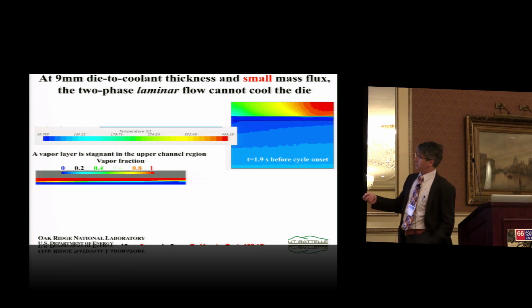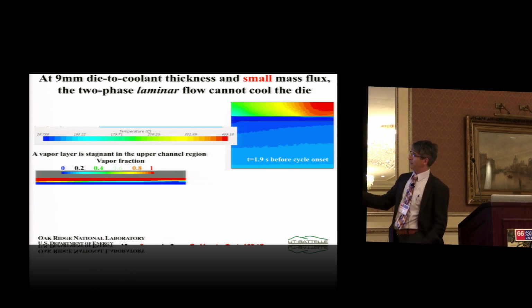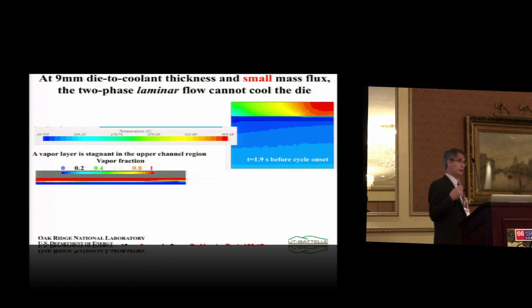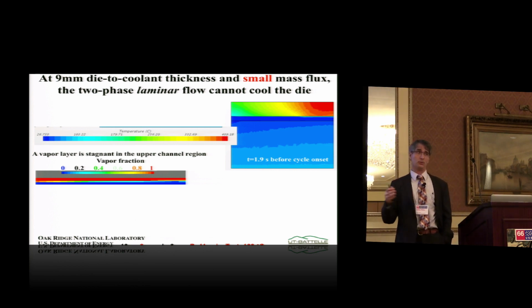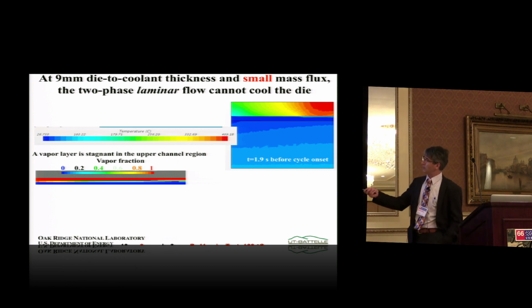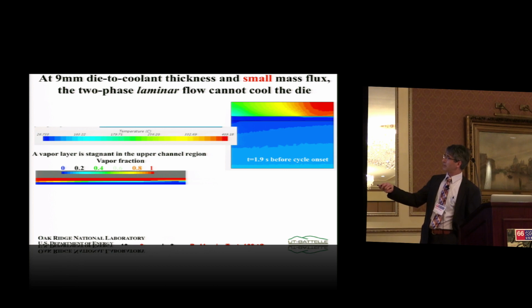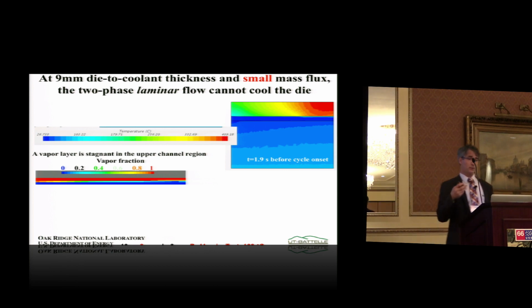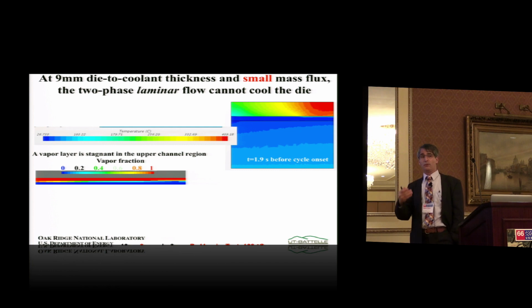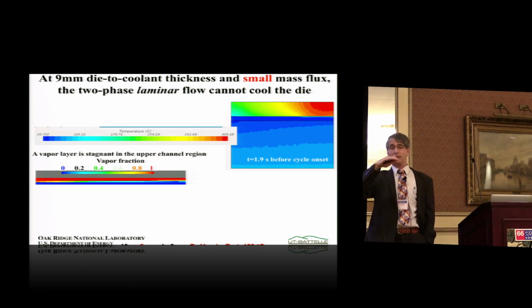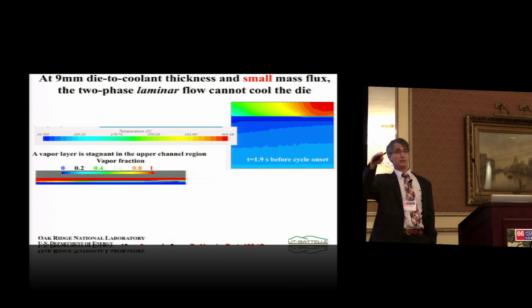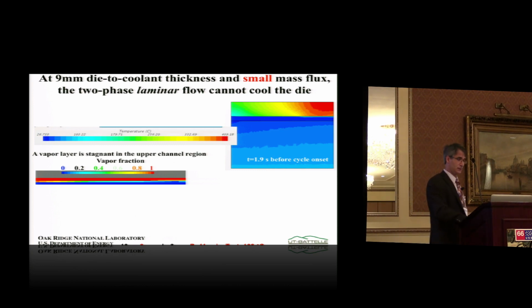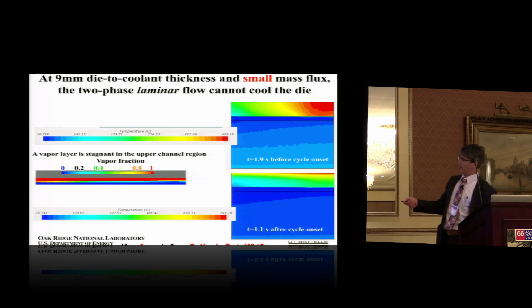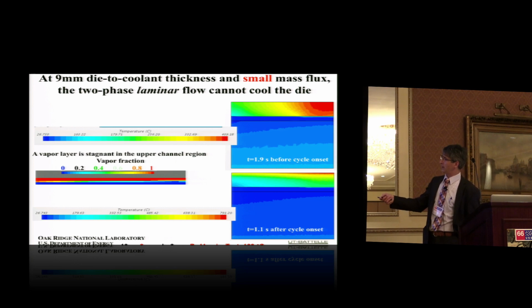And just want to mention here that we also take a look at the amount of vapor that's generated in that cooling channel. Sometimes we don't have any vapor. We discard that case. Sometimes, we have too much of it. And in this particular case, we found out at low, small mass fluxes that even before a new cycle will start, the top die right there is actually insulated by a thin layer of vapor. So it stays there, it doesn't get removed at all. So when the new cycle starts, no wonder that temperatures are going through a roof. We have about 790 here.